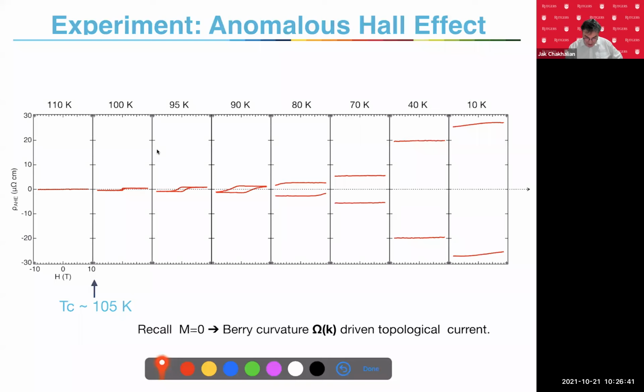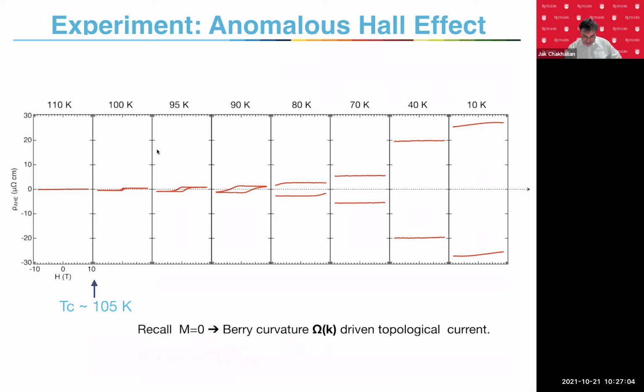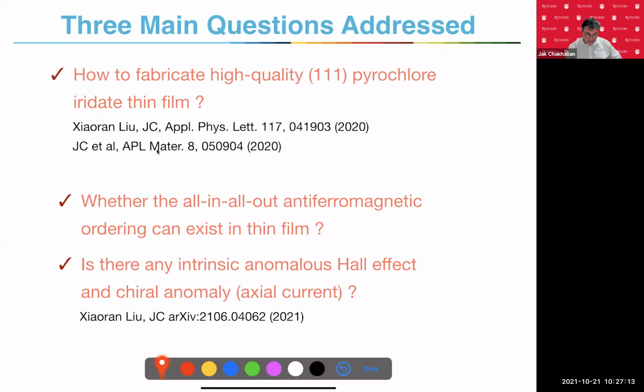Though I want to remind you again, this is a fully compensated antiferromagnet, which is m equals 0, and it cannot have this kind of hysteresis unless you really truly use the Berry curvature as a source of internal magnetic field, which is a kind of pseudo Lorentz force, if you wish. But in reality, it's really the topological current, and it really got gigantic: 23% of quantized conductivity in this material. So that's where I want to finish.